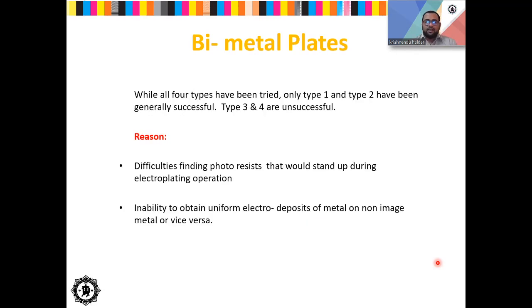But as I have already discussed, for bimetal plates, the type 1 and type 2 are generally successful. Type 3 and type 4 are not that successful. The first reason is the difficulty of finding a photoresist that would stand up during that electroplating operation. No matter how much hardened coating you produce during the process of your exposure, at the time of your electroplating operation, it's very difficult for this hardened coating to remain over the plate and to segregate these image and non-image areas.